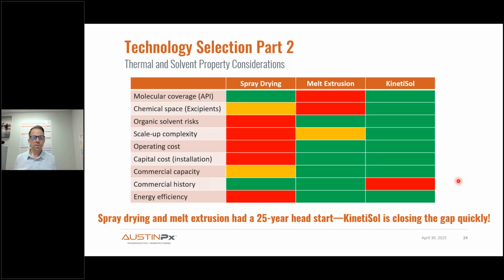So now let's look at part 2 of technology selection, thermal and solvent property considerations. So we like spray drying because the molecular coverage is excellent. I mean, if the drug's got even a little bit of solubility in an organic solvent, you can evaluate spray drying. So it's great from that perspective, and we know this. Now, when we look at the chemical space, though, what limits what you can do in terms of formulating an ASD is that the excipients have to be soluble in the same organic solvent as the drug, and that really limits what you can do in terms of formulation.